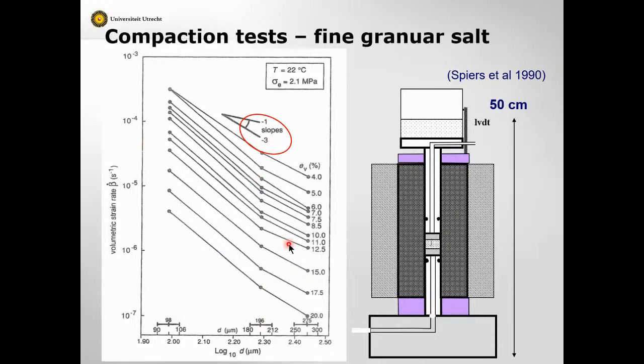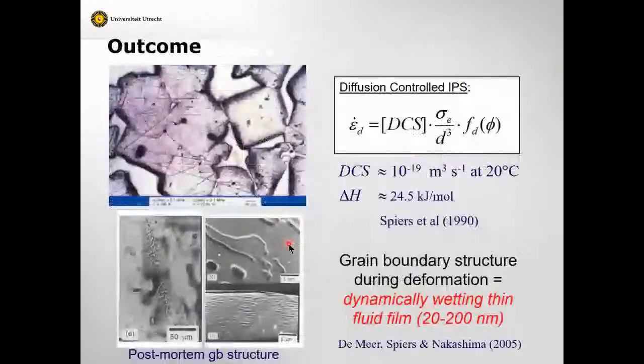So this really started to confirm what's going on. If you look, we looked at the microstructure, which is a key part of a microphysical approach. And what did we see in this granular salt that we compacted? Indentations of grains into each other and overgrowths where material precipitated in the pores.